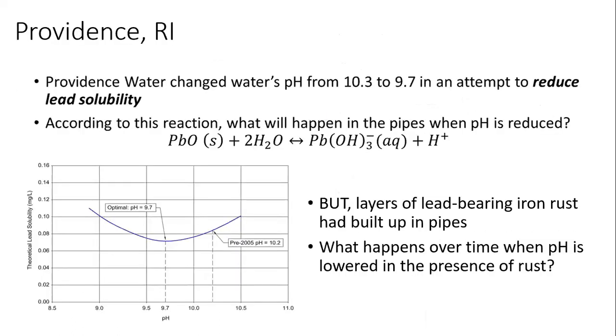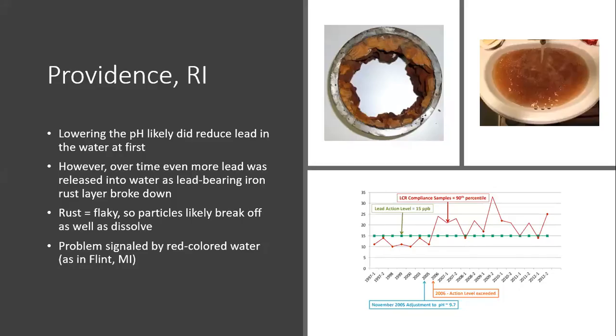Another case in the US was in Providence, Rhode Island. Providence water changed the water's pH from 10.3 to 9.7 in an attempt to reduce lead solubility. If you see the graph in the slide, lead solubility is the lowest at pH 9.7. But layers of lead-bearing iron rust had built up in pipes. Over time, this lead-bearing iron rust layer broke down, releasing lead into the water. This problem was signaled by red-colored water, the same as in Flint, Michigan.